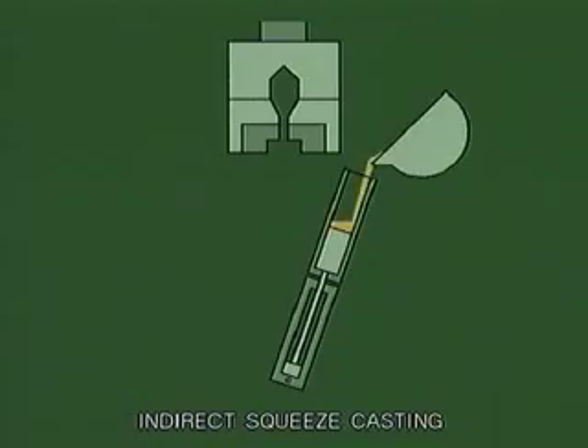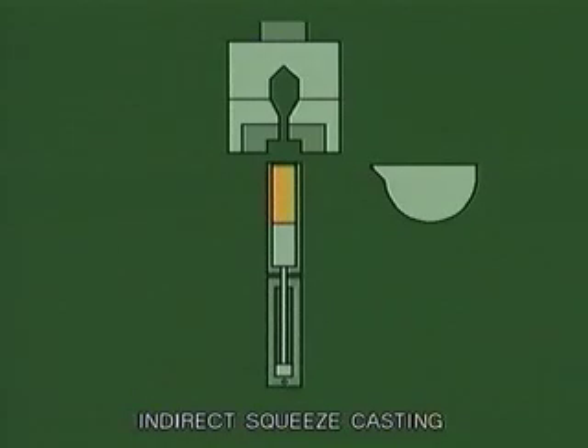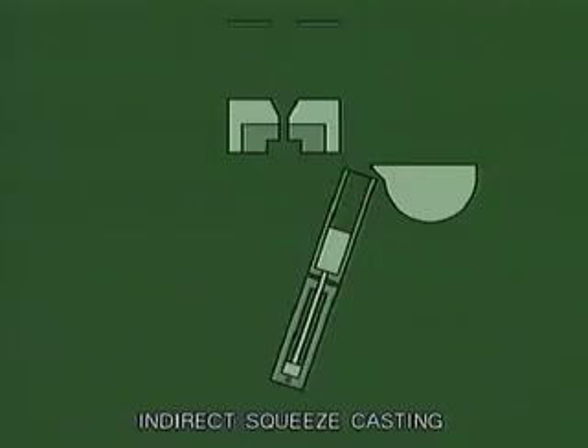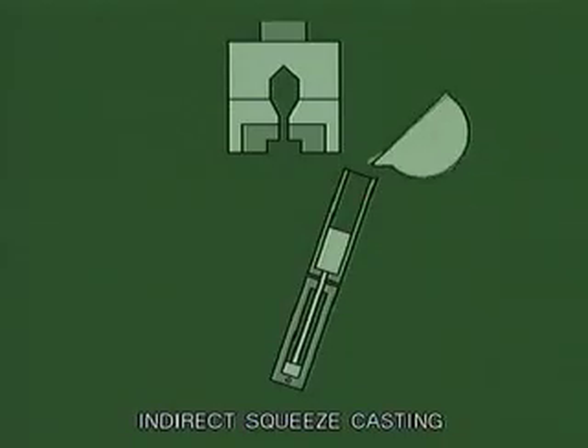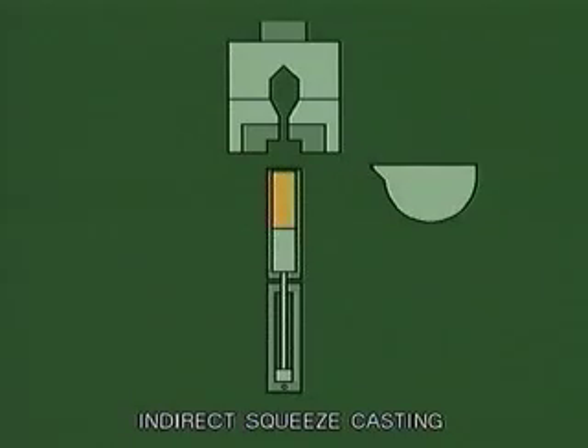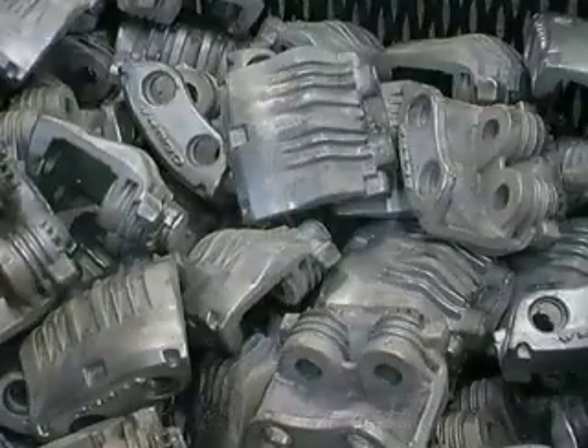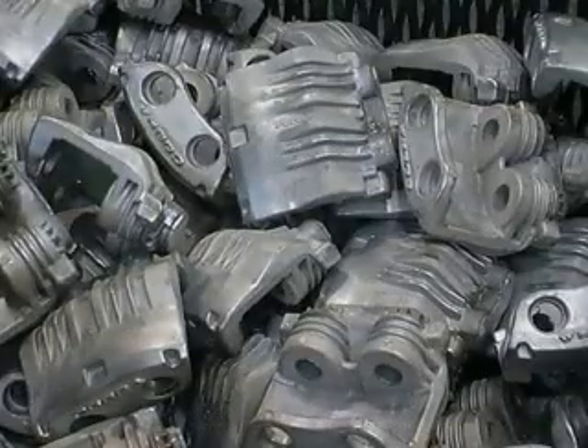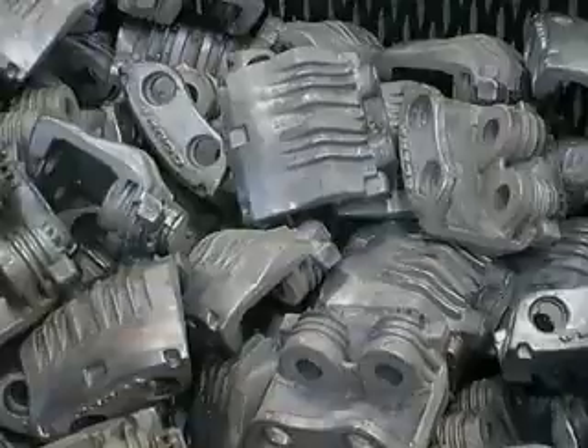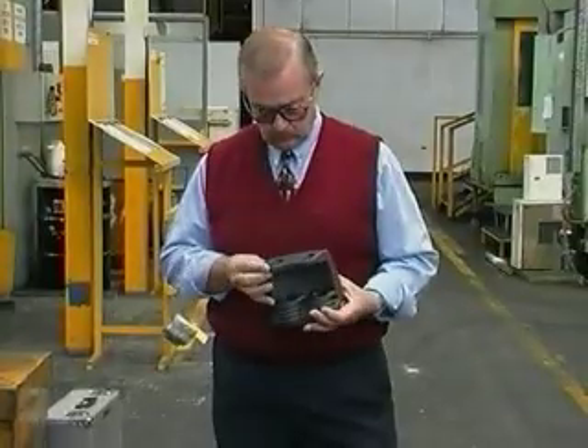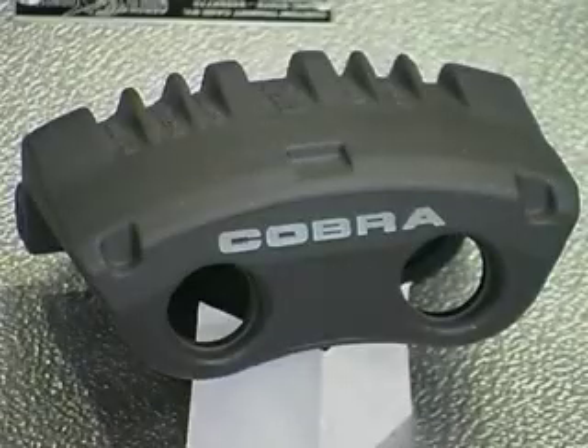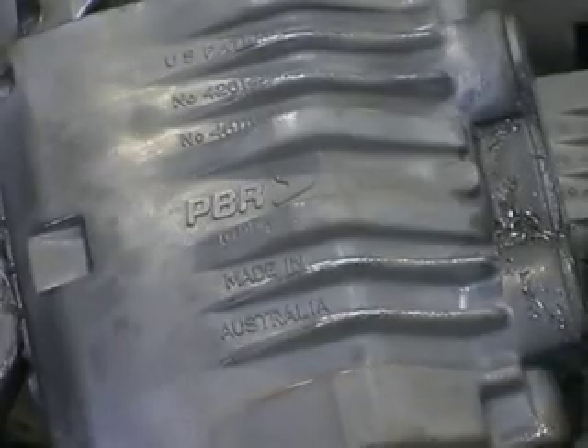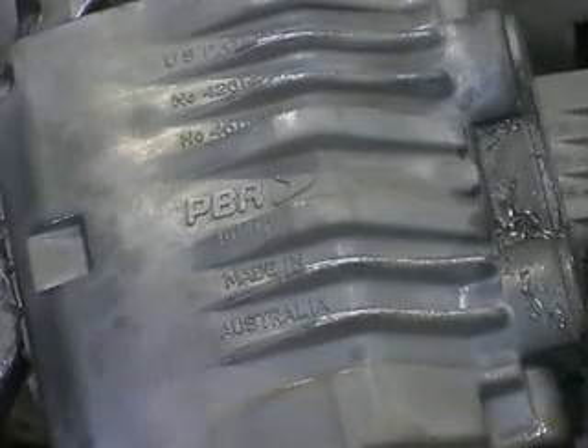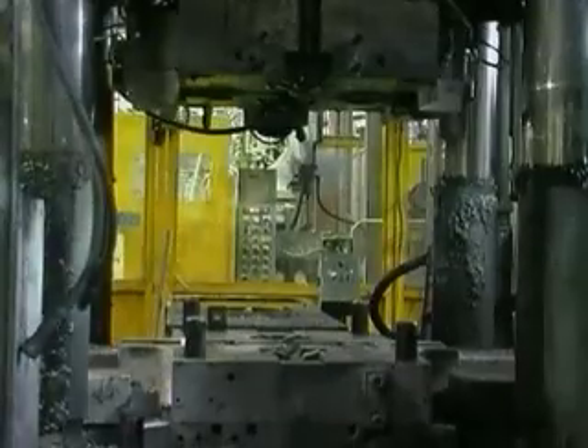The pressure is maintained during solidification, such that the process is akin to extrusion or forging. The close contact of the metal to the die increases cooling rates and reduces cycle time. However, die life is also reduced. These disc caliper components are required to have very high integrity to be able to be heat treated, have fine surface detail and close dimensional tolerances. In this situation, squeeze casting is an appropriate method of manufacture.